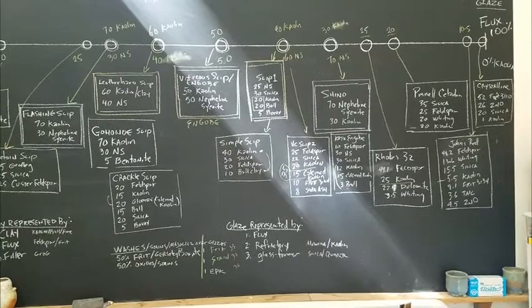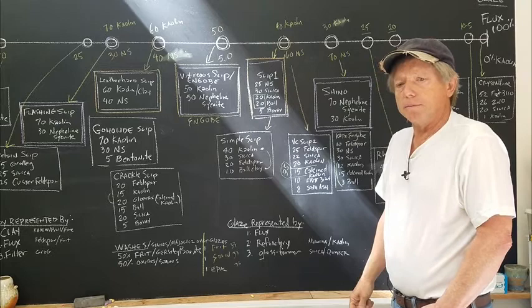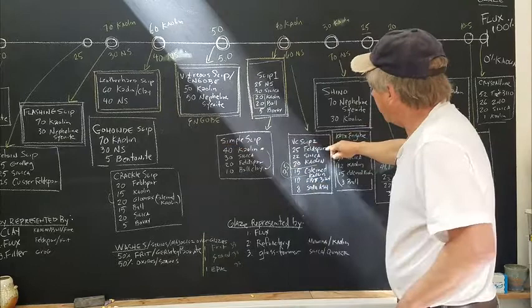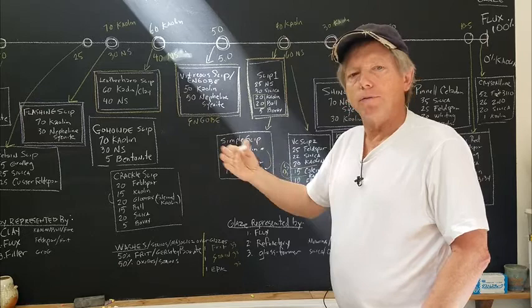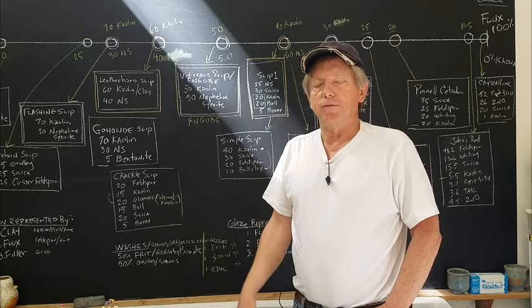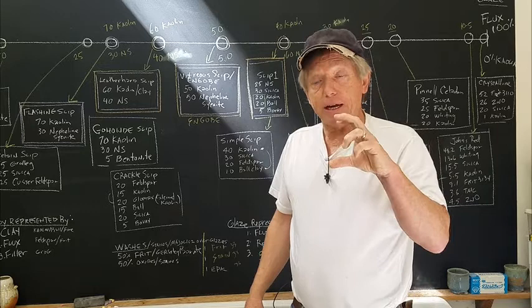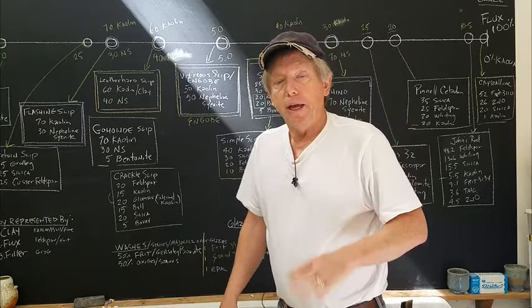Okay, so now we are into, if I see this recipe here, it's going to be an underglaze. I can immediately know that by how much clay is in there. In this case, a lot of times 40% versus 70 or 80. And this has calcined kaolin. A lot of these clays and slips and glazes have all evolved over the years. So when you start out in pottery, you're just sort of jumping in midstream. Somebody would have a slip and then they would notice it's flaking off. So they would take their clay component, say it was 40%, and just calcine half of it. That cuts the shrinkage of half of that clay. So now they only have 20% of the clay that's plastic and shrinks, and 20% is like bisque or non-shrinking. Then that would work, and that's how these all evolved.